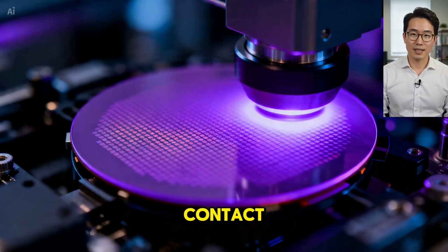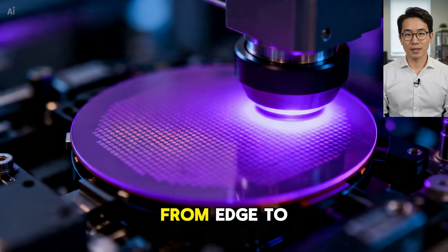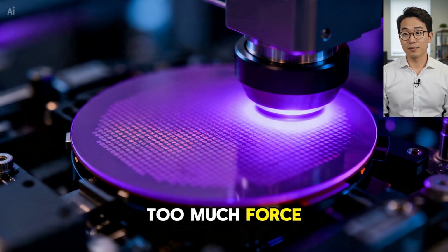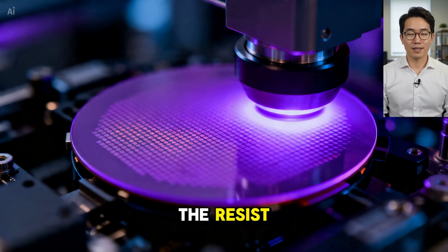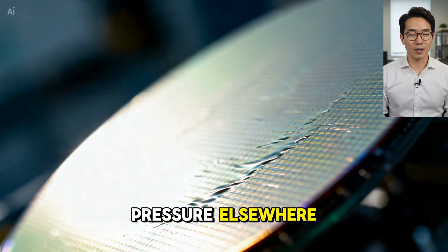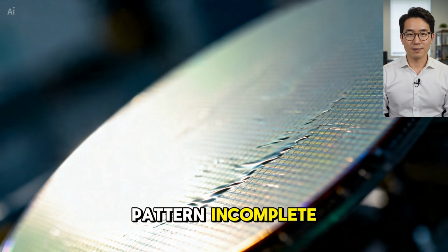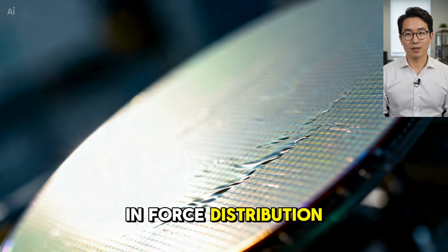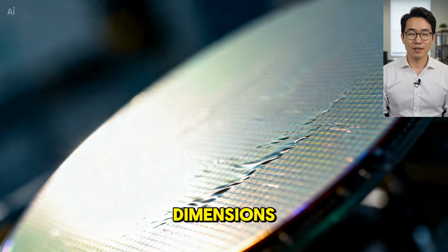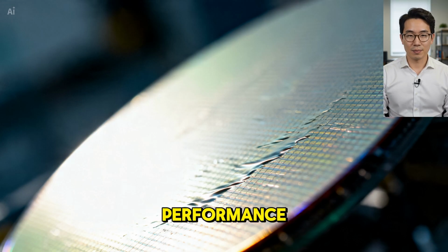Pressure control presents another major challenge. The template must contact the wafer with extraordinary uniformity from edge to edge. Too much force in one region can deform the resist, while too little pressure elsewhere may leave sections of the pattern incomplete. Even tiny differences in force distribution can affect feature dimensions, creating inconsistencies that reduce device performance.